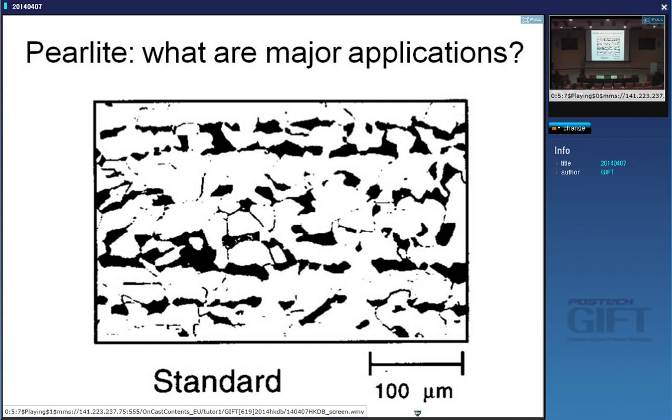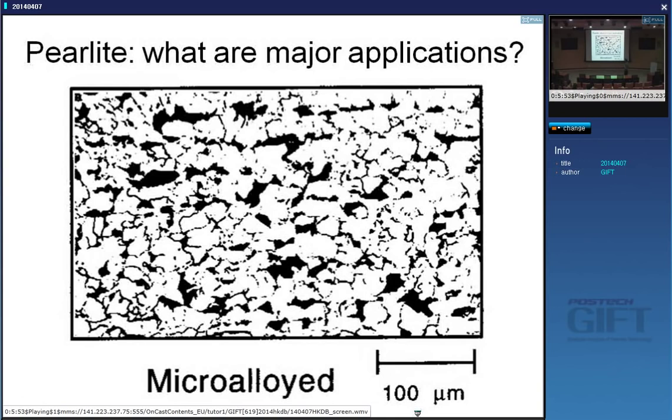And if you either cool rapidly or you process this differently, then you can get rid of this banding. Because if you cool rapidly, then ferrite will nucleate in all regions because there's enough driving force, and therefore you get a more uniform structure. So when we make pipelines for difficult environments where there's hydrogen-induced cracking and sulfide-induced cracking and so on, you really don't want these bands of pearlite. So they're accelerated cooled in order to reduce the amount of carbon segregation that happens because of the manganese segregation. And modern steels, which are microalloyed and processed differently, will show much less of the banding that we observe.